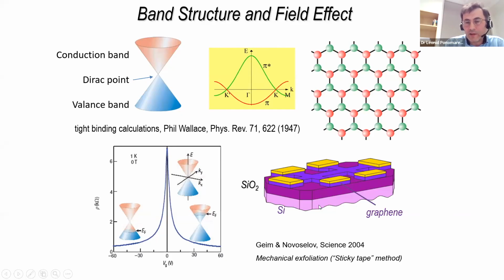So this is basically gate voltage. So this is the simplest field effect device, and they observed that resistance of graphene actually changes with gate voltage quite significantly. So exactly at zero gate voltage, resistance is largest. That's because the valence band is fully occupied and the conduction band is empty. So that's normal. Normal semiconductors are insulating if they are not doped.